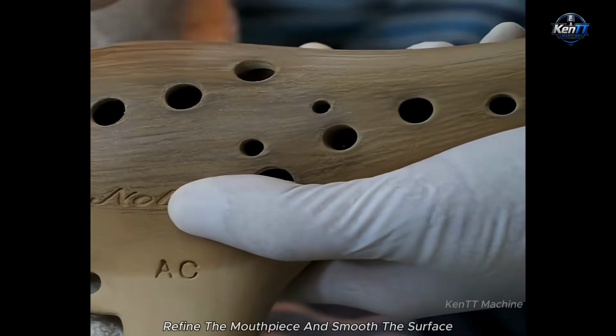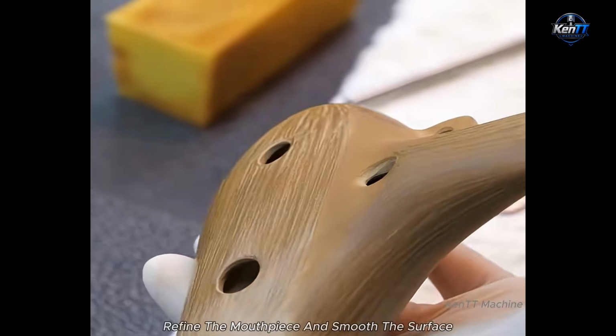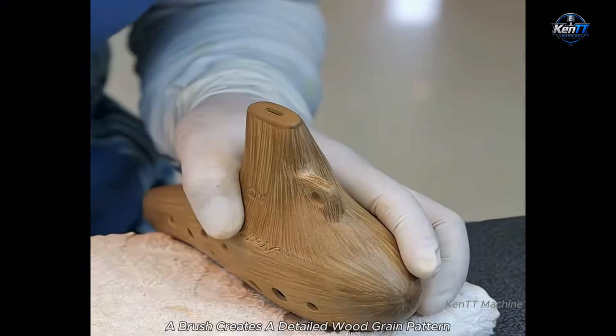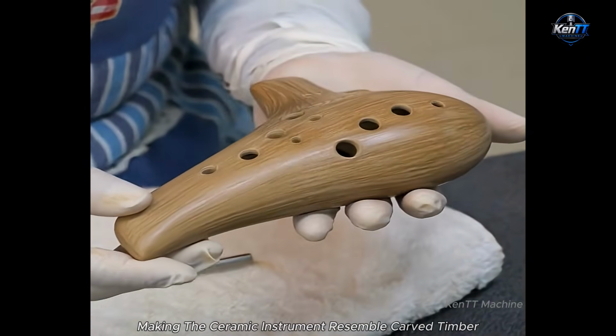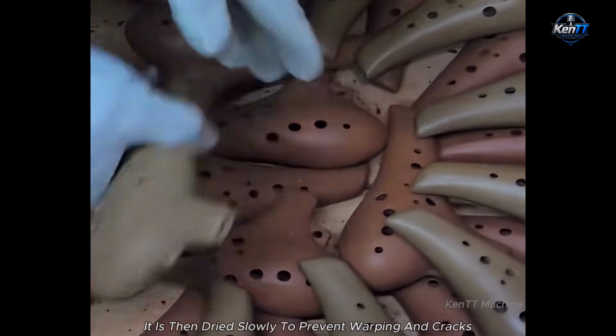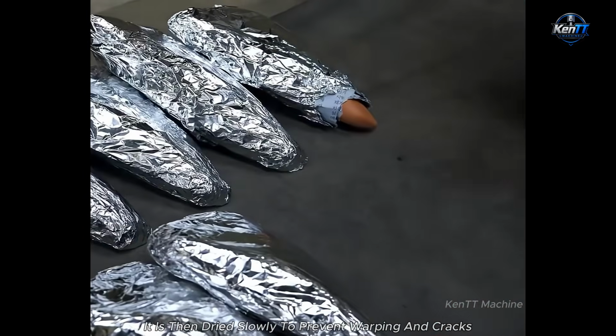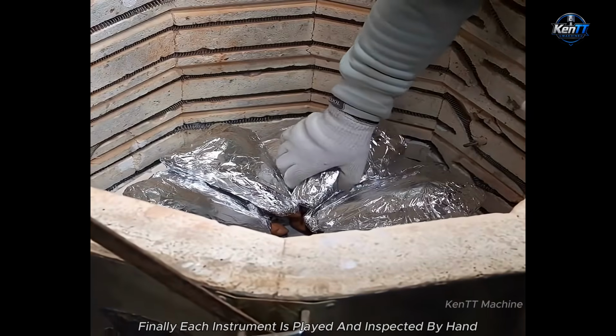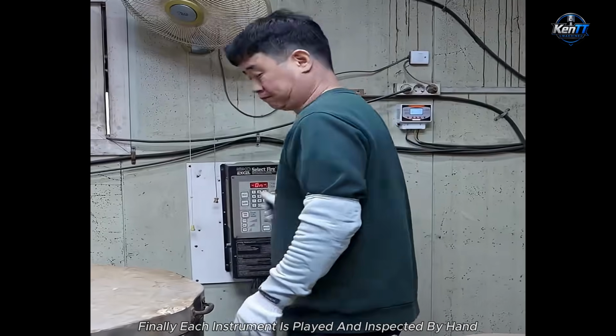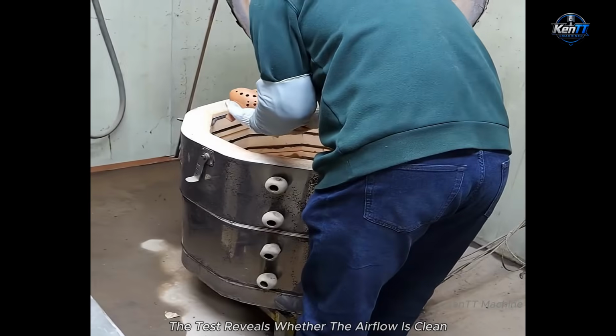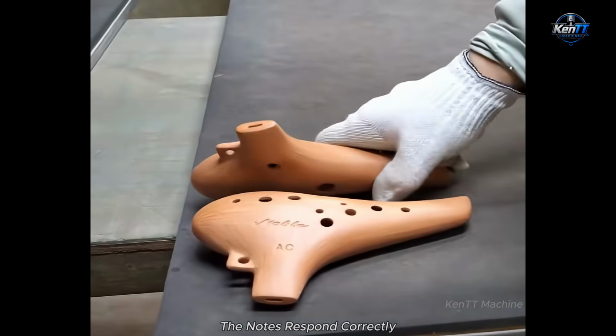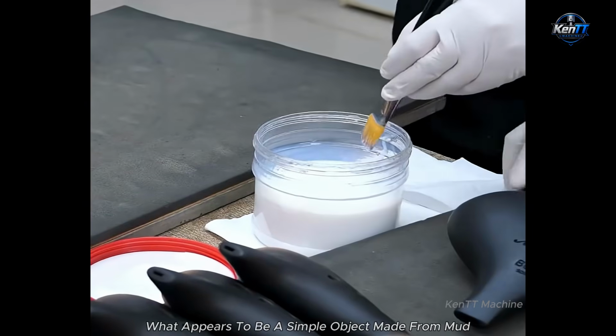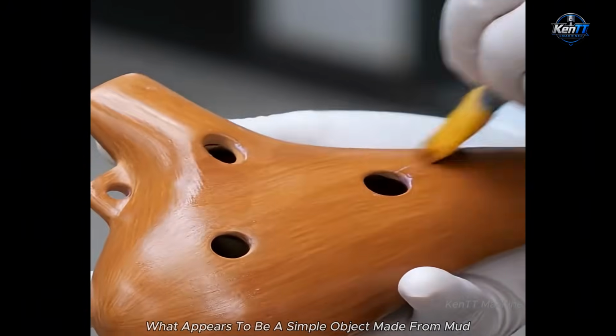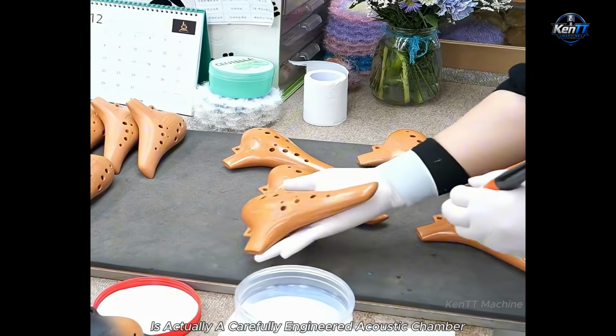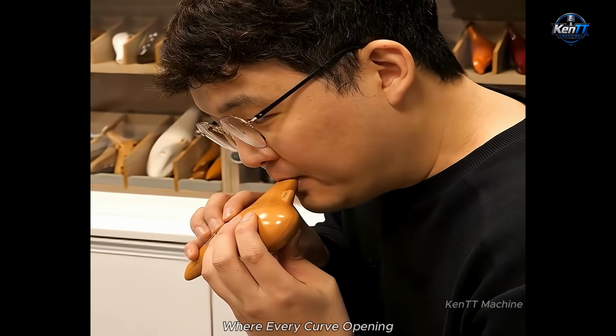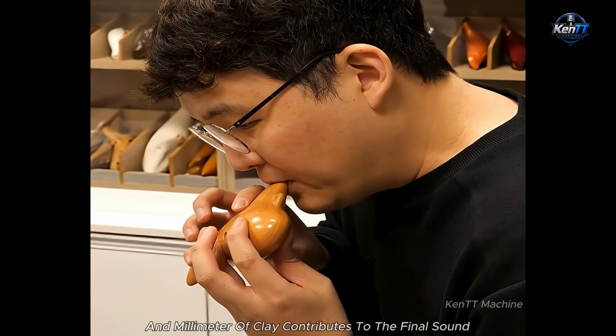Workers clean the holes, refine the mouthpiece, and smooth the surface. A brush creates a detailed wood grain pattern, making the ceramic instrument resemble carved timber. It is then dried slowly to prevent warping and cracks. Finally, each instrument is played and inspected by hand. The test reveals whether the airflow is clean, the notes respond correctly, and the tuning remains balanced. What appears to be a simple object made from mud is actually a carefully engineered acoustic chamber, where every curve, opening, and millimeter of clay contributes to the final sound.